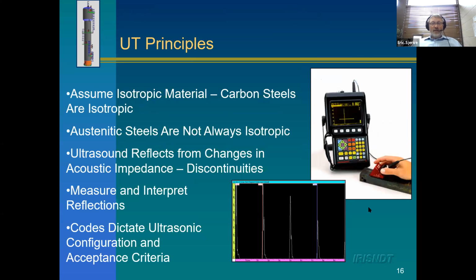With UT, there's a couple of things I see that result in bad work. With ultrasonic testing, we have to have isotropic materials. And carbon steels are almost always isotropic. Austenitic steels aren't. So you have to be real careful when you do ultrasonic testing on austenitic steels. That can lead to all kinds of bad work being done. And the code talks about that. That's in the ASME code.